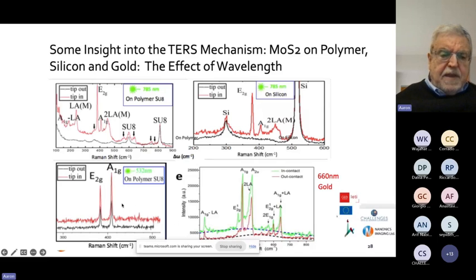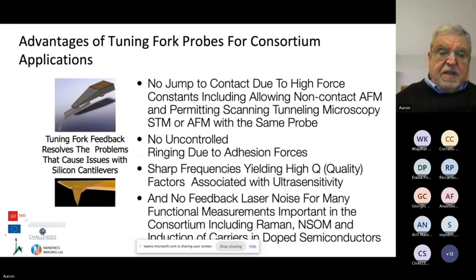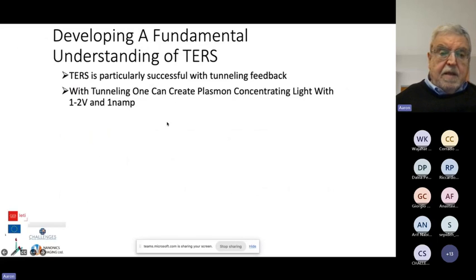But one of the things that is very definitive about TERS, nearly generally, okay, is the fact that the intensity only changes, not the frequency of the band. So one of the best methods actually to see TERS is STM. And as I said, these systems have no jump to contact, and you can flip between AFM and STM in the system, okay? So TERS is particularly successful with tunneling feedback, okay?